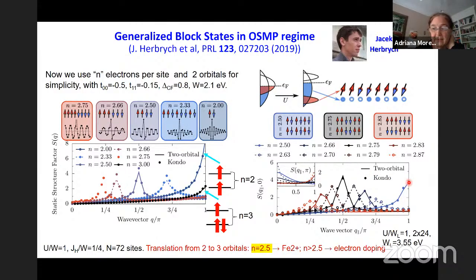But we did calculations in the ladder and found similar behavior. We start with the peak at pi, but then incommensurability develops, and we go from the pi-0 situation to the blocks. Here we see the blocks observed experimentally in barium iron selenide, and then we go to these more complex phases with blocks of size 3. There seems to be a lot of variations, okay?